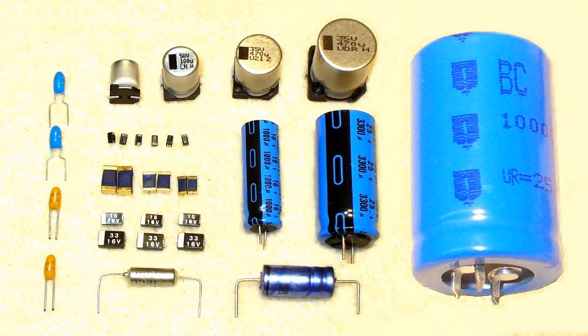Commercially available industrially produced tantalum capacitors now have reached as standard products the high MIL standard C level, which is 0.01%/1000 h at 85 degrees Celsius and UR, or one failure per 10^7 hours at 85 degrees Celsius and UR. Recalculated in FIT with the acceleration factors coming from MIL-HDBK-217F at 40 degrees Celsius and 0.5 UR is the failure rate. For a 100 microfarads, 25 volts tantalum chip capacitor used with a series resistance of 0.1 ohms, the failure rate is 0.02 FIT. Aluminum electrolytic capacitors do not use a specification in percent per 1000 h at 85 degrees Celsius and UR. They use the FIT specification with 40 degrees Celsius and 0.5 UR as reference conditions.